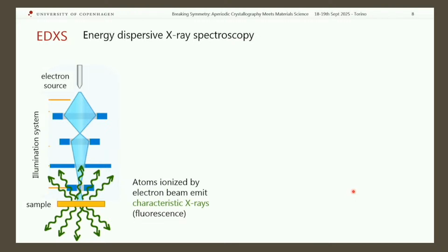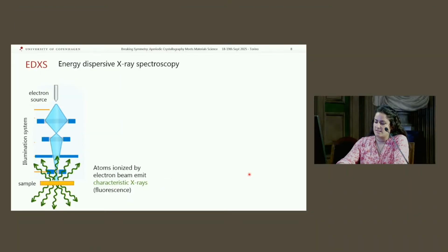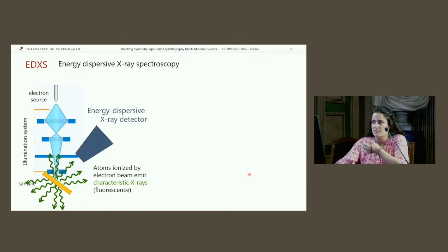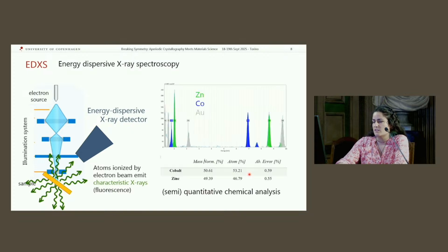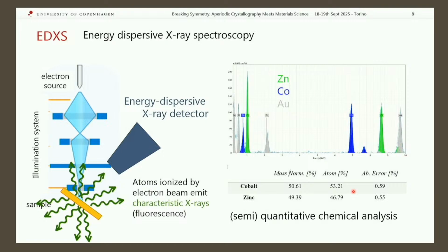So let's see some of the analysis we can do on this sample. We have seen that when the electrons interact with the sample, the atoms can be excited and re-emit X-ray fluorescence, and so we can just insert an X-ray detector in the proximity of our sample and analyze this emission. The X-ray fluorescence is extremely characteristic, like a fingerprint of every atom type. So we can separate these emitted X-rays in energy, and we can then identify the atom types. And also with suitable calibration, we can do a quantification. So we have our chemical analysis.